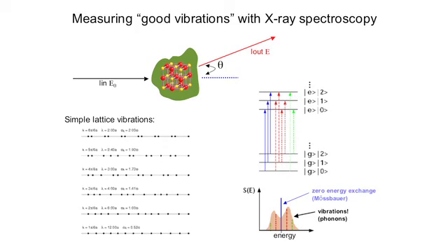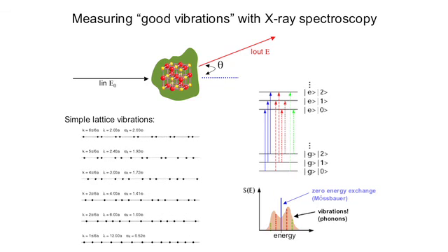So how do we do these measurements? We introduce an X-ray with a very specific energy that interacts with the lattice that is vibrating. So it interacts with these motions. And after that interaction, it is changed in energy. And that energy change is proportional to a specific vibration.